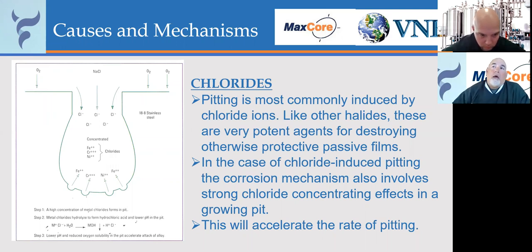So a lot of times when you go in and you start to repair something like this, if you're going to go in and do some mechanical polishing and try to repair this, many times you can start grinding on that and you'll see that pit grow and get much larger. And that's the reason. It's because it has eaten out much more of this and become more anodic. So you may end up at some point in time even having to go in and fill those pits with weld material in order to fix that if you're doing a field repair.